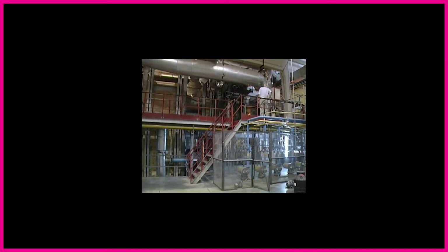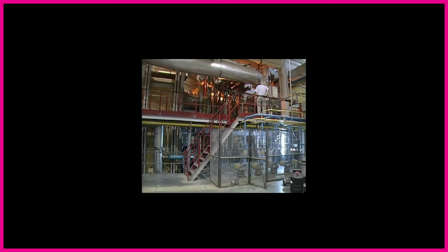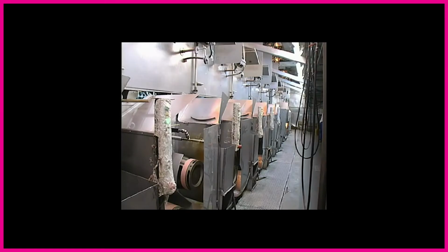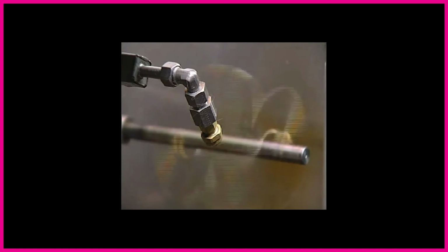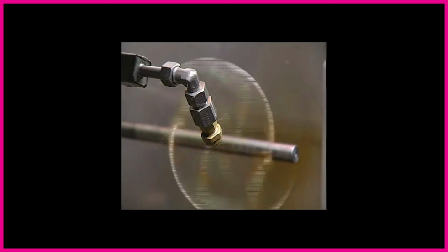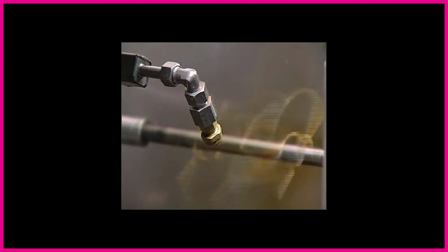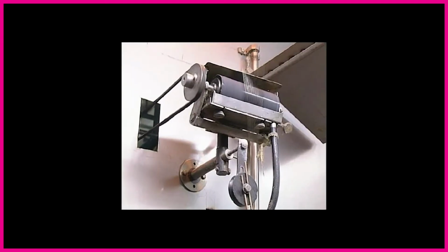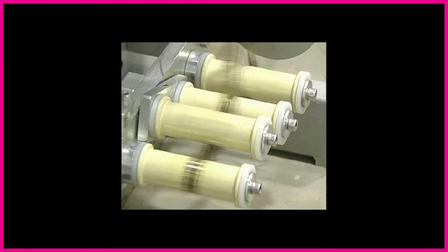First, the quarried basalt rock is crushed into a fine material. This material is then placed into a melting bath, which is heated to around 1500 degrees Celsius in a furnace to turn the rock back into a liquid form. That liquid rock is then extruded through a series of dies, forming a continuous strand of fiber. There are no additives, no complex pressurized heating. It's just the raw molten rock extruded into that fiber. Now, as with carbon fiber, the single strands are then bundled together to create a usable basalt fiber. These bundled fibers are then laid up in exactly the same way as carbon fiber.